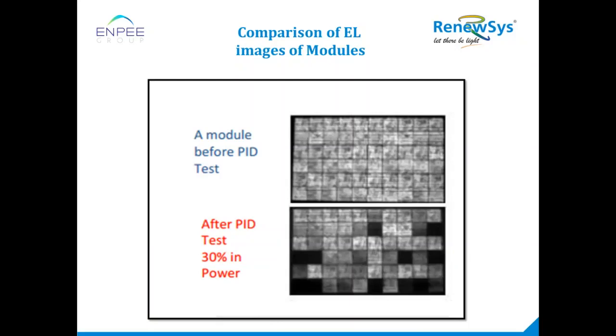If you take a glass-to-glass module, we have two rigid surfaces on top and the back. So some module manufacturers will not have the frame, but there are other issues. In glass-to-glass modules also, nowadays a thinner frame is coming into the picture, but an aluminum frame is there. The moment we have a frame, the effect is the same on both glass-to-glass as well as glass-to-backsheet modules. If glass-to-glass modules do not have a frame, then the problem of PID is not there. Whereas a glass-to-backsheet module always has a frame, so this effect is always there. Okay, so we can infer that if a module is a frameless module, it is unlikely to have PID. Would that be accurate? Yes.